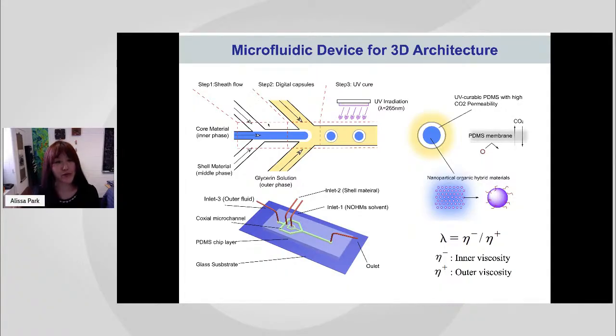So we were able to provide the blue fluid, which is NOHMs-like material or NOHMs, a highly viscous fluid. And the white part is the UV curable polymer. By creating a droplet inside a droplet, in the second stage we do UV cure. So then now you have a solidified shell, which is gas permeable, and the blue color, which is a liquid solvent. It's a higher viscosity, but has excellent CO2 capture capacity, and selectivity is intact.